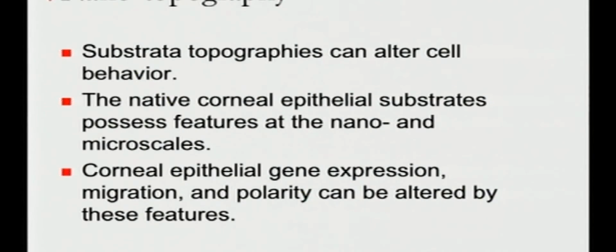We've decided to modify these silk films to make them better than amniotic membrane. We just don't want a replacement, so we're using nanotopography, to create small topographies on the surface, much like you might find in native tissue, that helps guide gene expression and change the behavior of cells. We use a process called soft lithography to take nanoscale features from a silicon wafer, transfer that to a silicone mold, and then make these films.